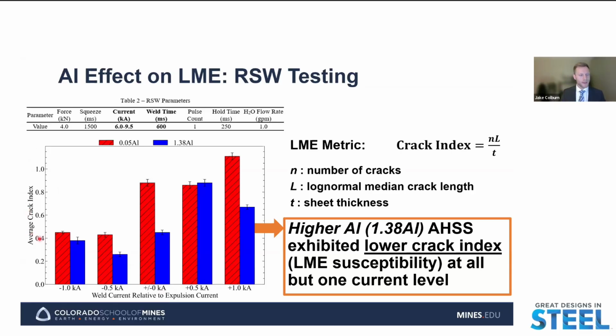We're comparing the average crack index of these two alloys at different weld currents relative to the expulsion current. And we're comparing relative to the expulsion current to try and compare these welds at relatively equal heat inputs because these two alloys are going to have different expulsion currents due to the higher alloying addition in the high aluminum alloy. But we see here that the higher aluminum alloy exhibited a lower crack index or lower LME susceptibility at each of these current levels, except for one in which at the 0.5 kiloamp condition, we see relatively equal LME susceptibilities or crack indexes for the two alloys.